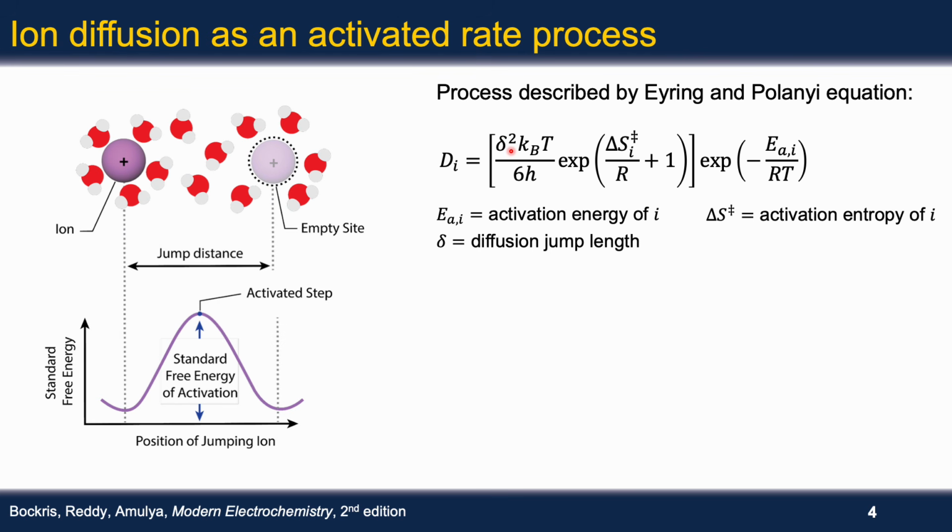In our study, we're using the size of a water molecule for this parameter. So essentially, when an ion diffuses in the membrane, it displaces one water molecule in a diffusion step. There are some studies that use the membrane thickness for this parameter, but I don't think that's quite accurate because that would suggest that the ion is essentially crossing over the membrane in a single diffusion jump.